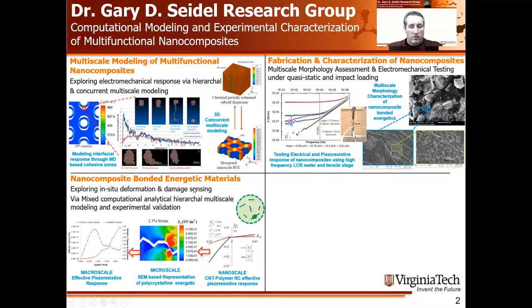In the energetic materials, we distribute the nanotubes in the binder and get a nanoscale piezo-resistive response, which is then passed to the microscale where we simulate fracture response and mechanical loading. We then pass this microscale representation to the macroscale where we can get a macroscale stress-strain response and correlate that with an increase in resistance response due to strain sensing first and damage sensing second.